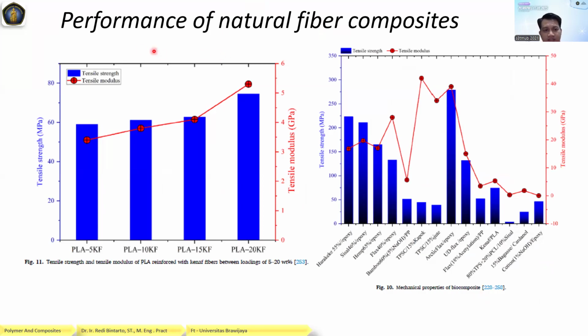Natural fiber composite performance from the journal. The highest strength is PLA 20 kenaf, yeah. This is PLA reinforced with kenaf fiber between loading 5 until 20%. So if 20% kenaf fibers, the tensile strength is higher. The proportion of kenaf fiber can increase the tensile strength and the tensile modulus.